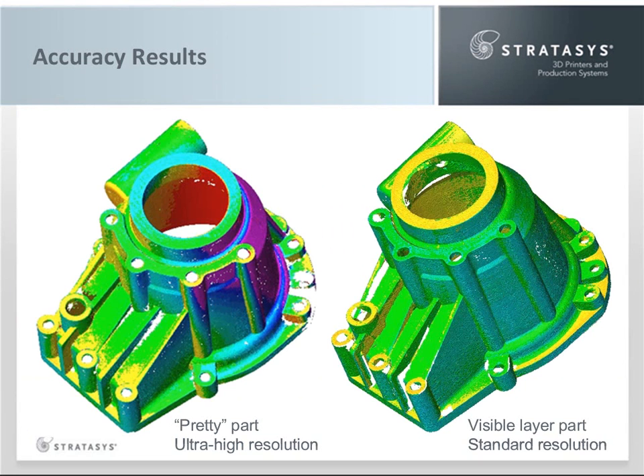Take a look at the color maps. 3D scanning data that is color-coded point by point to show how true to the design the additive manufacturing parts are. The red areas are oversized by 20 thousandths of an inch or more. The purples are undersized by 20 thousandths of an inch or more. The green areas are within plus or minus 5 thousandths of an inch, and the little bit of yellow on the right-hand image, it's about 7 thousandths of an inch oversized. This is just one example that shows resolution does not equal accuracy.